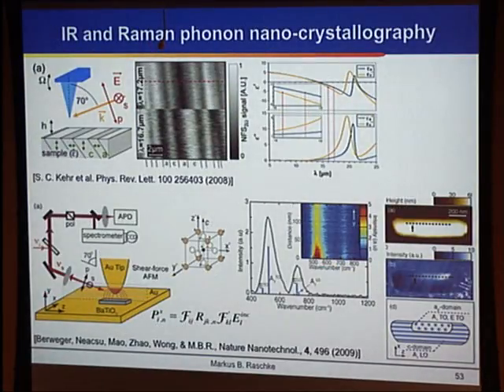This is analogous to what we can do also in soft matter. We can do it with the Raman tensor in solids. We've actually done this in ferroelectrics, being able to map spatially ferroelectric domain order by the phonon selection rules in nanocrystals, depending then on the crystallographic axis. Certain phonon Raman modes or phonon modes are Raman allowed, others are forbidden.